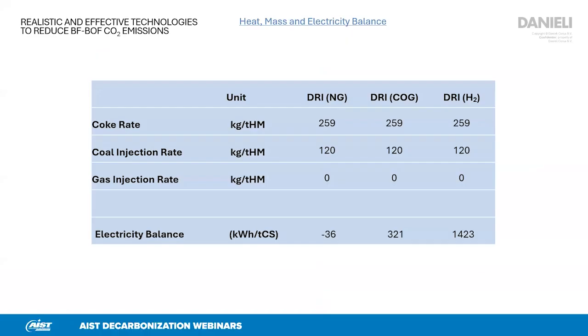And let us again look into the KPIs of the blast furnace when charging either DRI made by natural gas, or DRI made by coke oven gas, or DRI made by hydrogen. Again, you can see a coke rate reduction, which is similar for all three scenarios. We have reduced the coal injection rate somewhat. The reason is mainly the fact that we would then produce a little bit more coke. Also, we didn't want to violate the lower limit to the coke rate, which I already shared before. And the more coke we would charge, the more coke oven gas we could produce. And this balances out to the 30% I've already been mentioning before. So if more coke oven gas would be available to the industry, then the 30% that we have been assuming could be raised to 35, 40%, even beyond. But in reality, there are limits to the availability of coke oven gas.